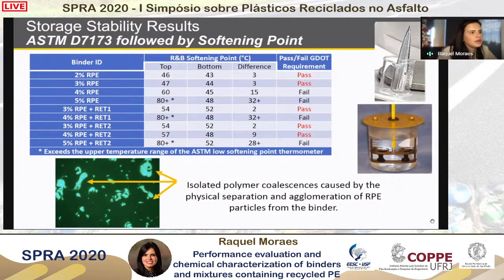recycled polymers in comparison to terpolymer number 1. However, terpolymer 2 still fails to accommodate the highest percentage of recycled plastics that we tried to evaluate. That was the 5%. As you can see, we fail when we have 5% of recycled plastics and the addition of the terpolymer number 2, meaning that this percentage of 5% of recycled plastics, in our experience with the projects that we have been working on, is way too much to be accommodated in the asphalt binder as modifier.